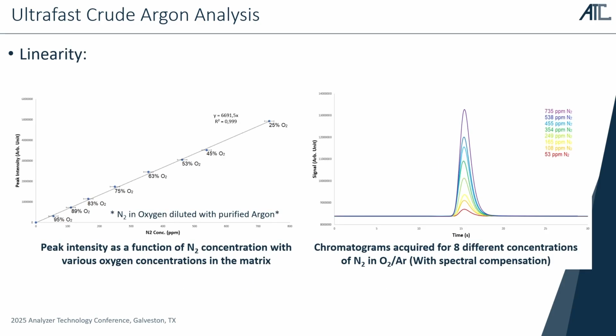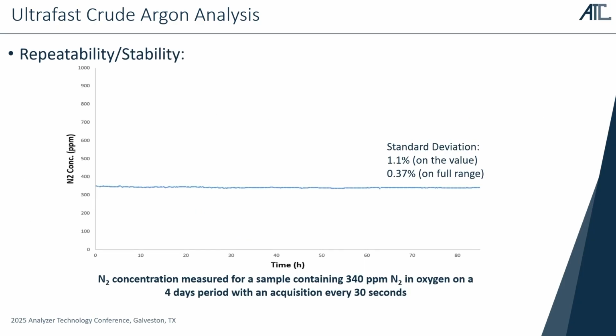And here you see some linearity data, and it shows that from 0 to more than 500 ppm, the nitrogen reading is going to be linear, and this is regardless of the oxygen-argon ratios, because the spectral compensation is going to compensate for the oxygen concentration. And here are some repeatability data that were acquired over a 4 day period with an injection every 30 seconds. So it shows that this method is very stable and repeatable.